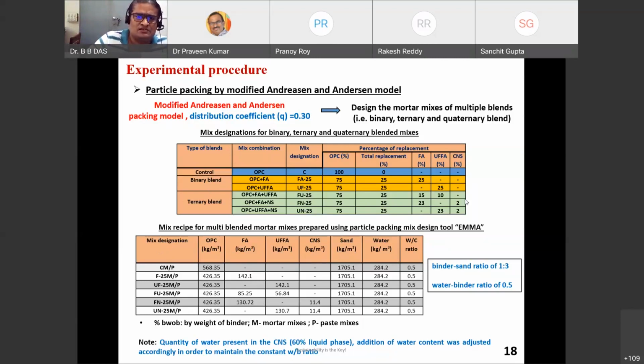Now this is the designation of the systems. We have gone for control, that is without any addition of materials. Then the binary blend, which is only OPC plus fly ash and OPC plus ultrafine fly ash. The ternary blend is OPC plus fly ash plus ultrafine fly ash. Then OPC plus fly ash plus nano silica, and OPC plus ultrafine fly ash plus nano silica. You can see OPC in the binary and ternary blends is fixed at 75%, and 25% is the total replacement.